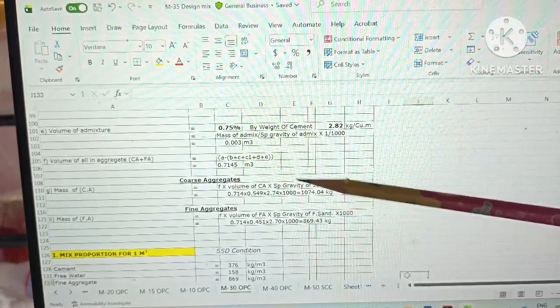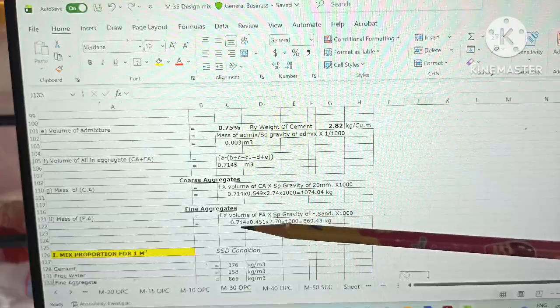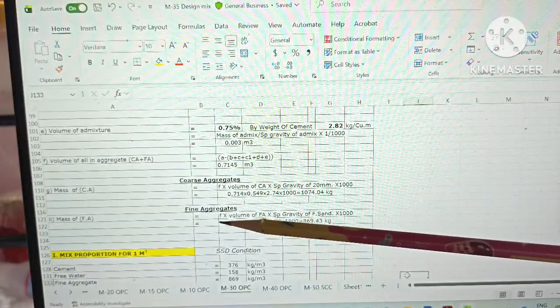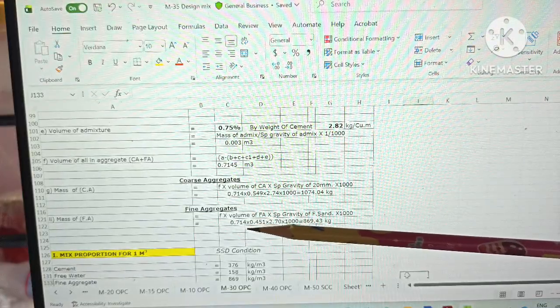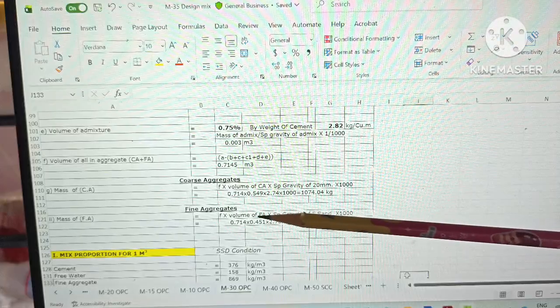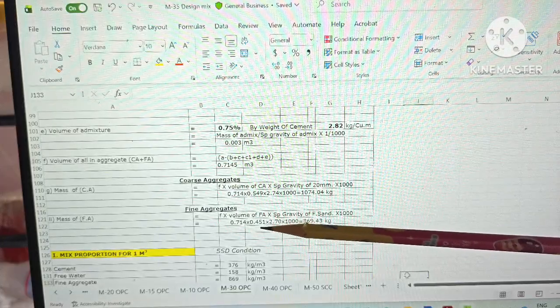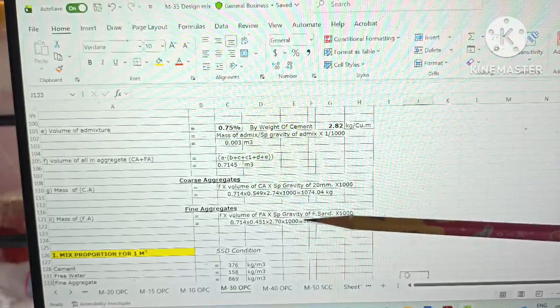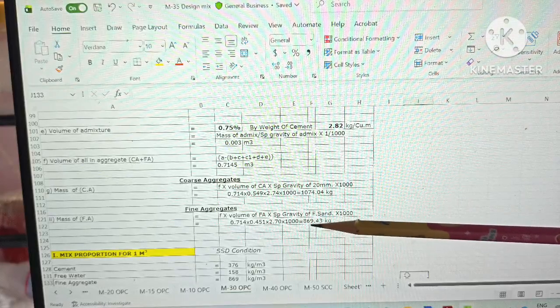1074.04 kg. Similarly, the mass of fine aggregate can be found in the same manner, where F is volume of all-in aggregate, that is 0.714, into volume of fine aggregate, that is 0.451, into specific gravity, that is 2.70, into 1000, and our final answer is 869.43 kg, that is mass of fine aggregate.